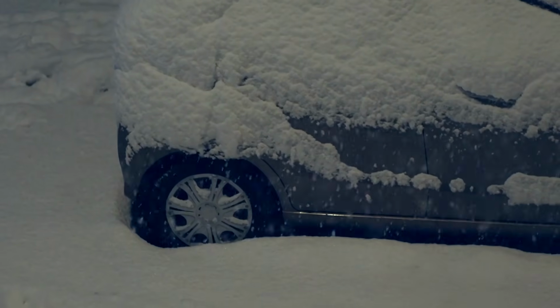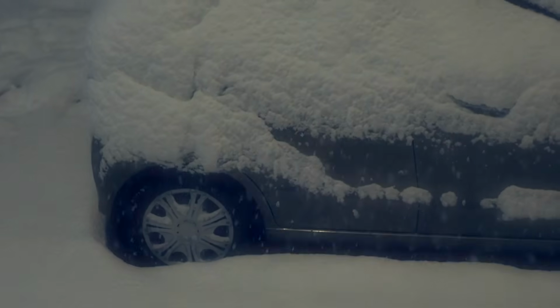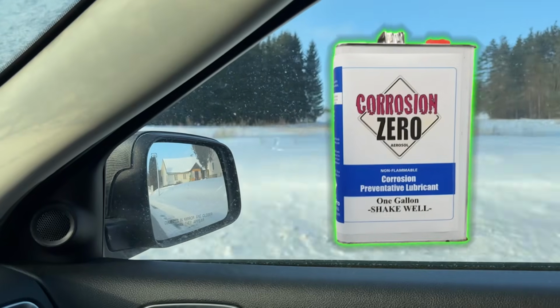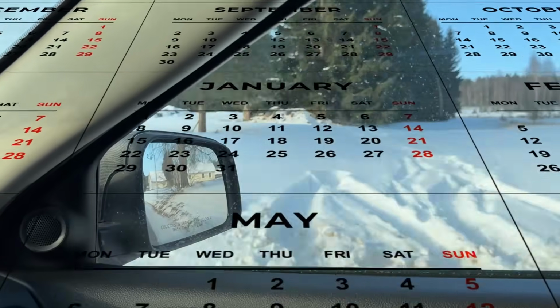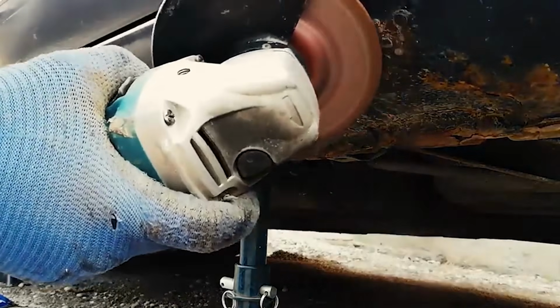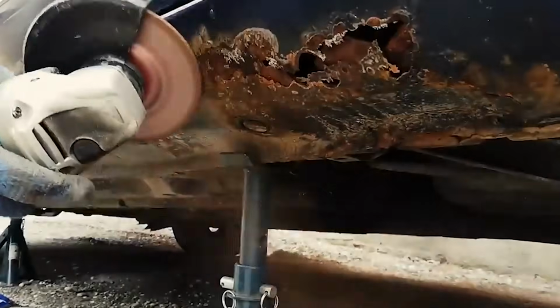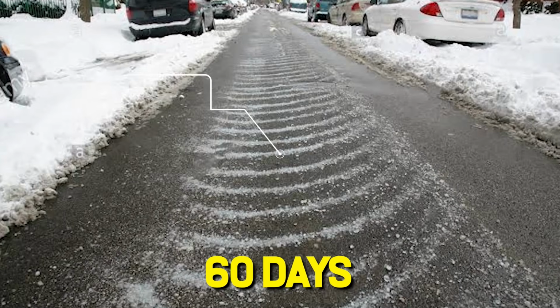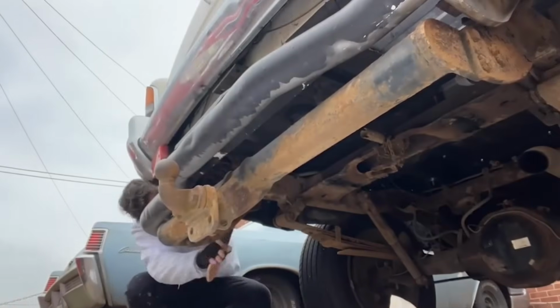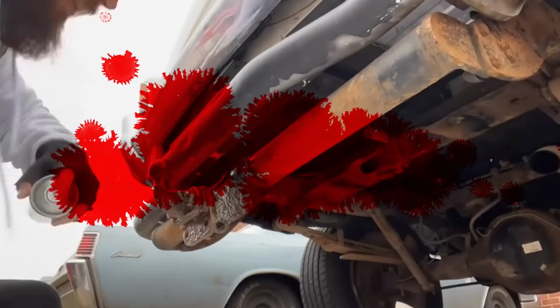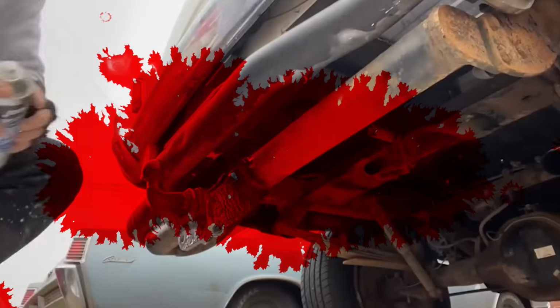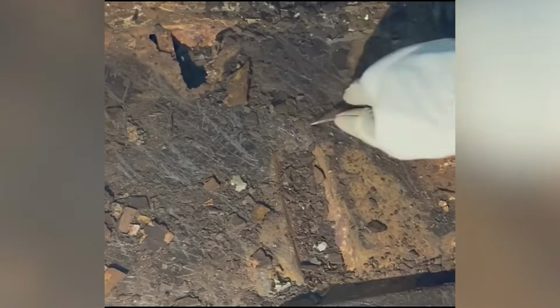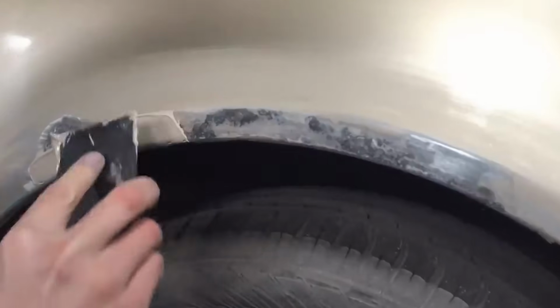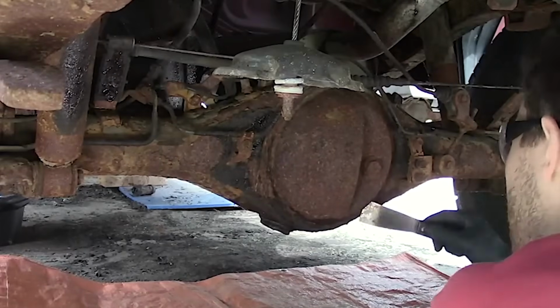In our winter testing, test panels with sealed seam joints treated with Eastwood internal frame coating showed zero corrosion at the seam interfaces after one complete winter. Identical panels without the internal coating showed visible rust development at seam interfaces within 60 days of initial salt exposure. The product's limitation is that it is not a suitable top coat for external undercarriage surfaces. It is formulated specifically for internal cavity protection. Used in its correct application context, it is the most effective rust prevention product in this entire investigation for the specific surfaces it is designed to protect.